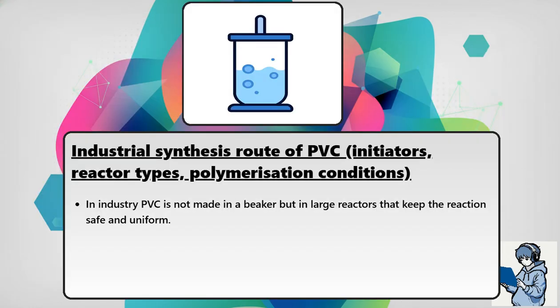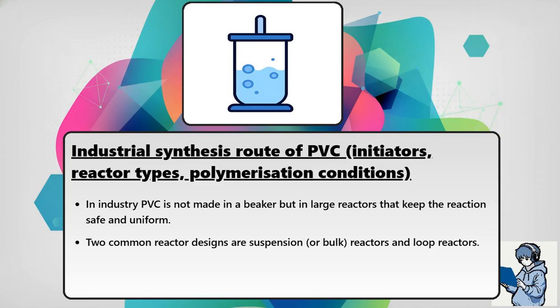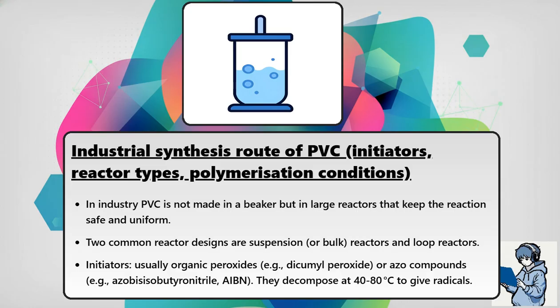In industry, PVC is not made in a beaker, but in large reactors that keep the reaction safe and uniform. Two common reactor designs are suspension or bulk reactors and loop reactors. Initiators are usually organic peroxides, for example dicumyl peroxide, or azo compounds, for example azobisisobutyronitrile, AIBN. They decompose at 40 to 80 degrees Celsius to give radicals.